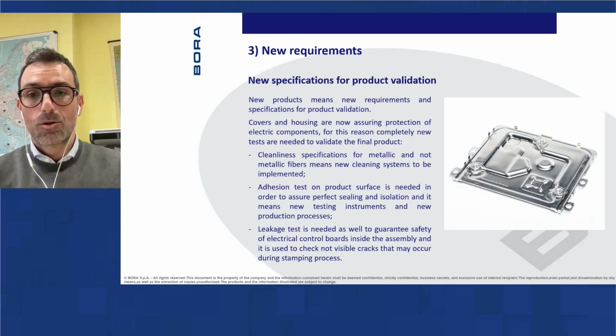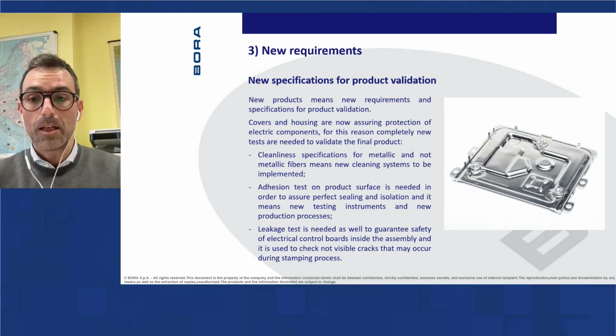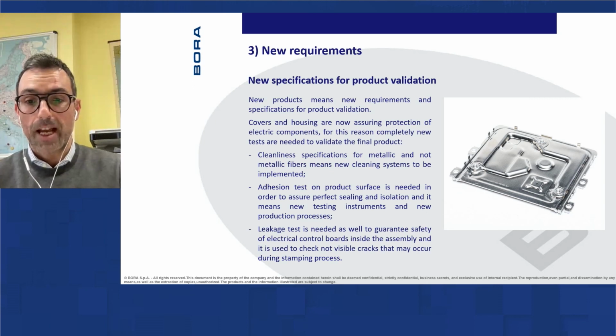It means that also very small cracks that are not visible can be critical for this kind of components. So it is needed also a leakage test to check that there are no cracks in the stamped parts at the end of the stamping process.